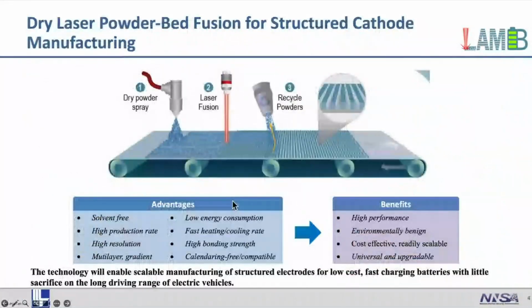So what we are doing right now is to develop a laser-based dry processing approach. How it works is, we're starting from very conventional lithium-ion battery electrode materials like NMC, PVDF, carbon black, those powders. We mix them into a uniform powder and then use electrostatic spray coating to dry coat those powders into a layer onto the aluminum foil, and then use a laser to apply the heat onto the powder layer, and that selectively melts the binder and bonds those materials onto the substrate.